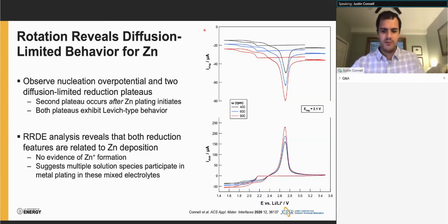I won't show it here, but if we do a corresponding experiment where we hold the ring electrode at very positive potentials, we don't see any evidence of reoxidation of a solution species such as a monovalent zinc ion. So we don't really see any evidence of Zn+ formation. What the voltammetry tells us is that there are multiple solution species leading to the deposition of zinc metal in this system.